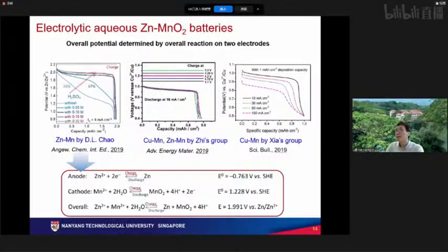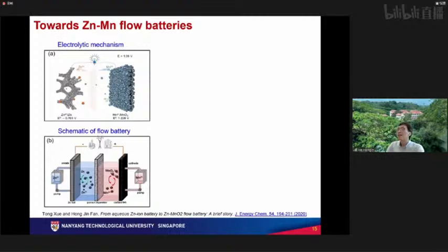very, very nice plateaus. And immediately after, Zhi Chunyi's group at City University of Hong Kong also found similar mechanisms, as well as Professor Xia Yongyao's group at Fudan. In Xia Yongyao's group, they also predicted that it's possible to have electrode-free batteries. So that's basically redox flow batteries. The important thing here is to control the pH values and the concentration of the manganese sulfate. Okay. And because of that, I would say that this is very good news towards zinc manganese flow batteries.